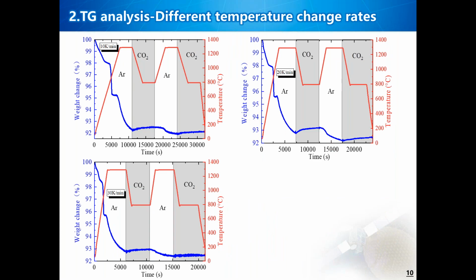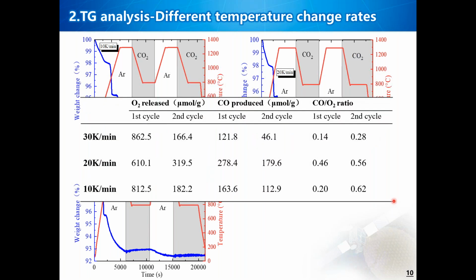And to determine the effect of heating rate in the thermochemical cycle, the rate changes of 10, 20, 30 degrees per minute were used. An approximately 13 milligram sample was used in the experiment, and as shown in the figure, in the first cycle, oxygen released at 3 heating rates was almost the same, but carbon monoxide production at 20 degrees per minute was about twice that at 30 degrees per minute, and 1.5 times that at 10 degrees per minute.